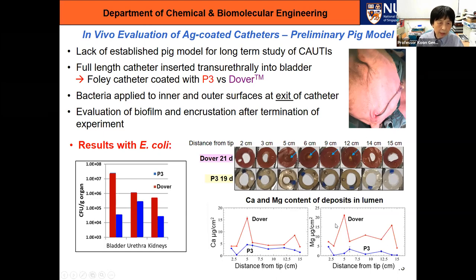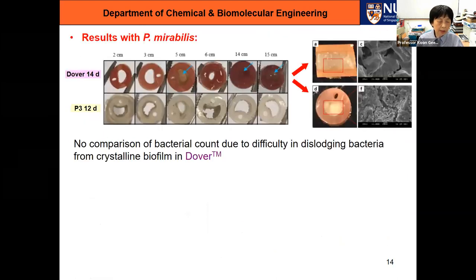But we know that the real test is actually P. mirabilis, so we did that also. As I said earlier, this bacteria is very hard to handle. It causes a high mortality rate and so on. In this case, for the Dover, the catheter is completely blocked after 14 days, so it's not possible to continue the experiment anymore. You can see from the microscopy images that the crystals have completely filled up the lumen. And this is what it looks like. On the microscope, you can see the crystalline structure.